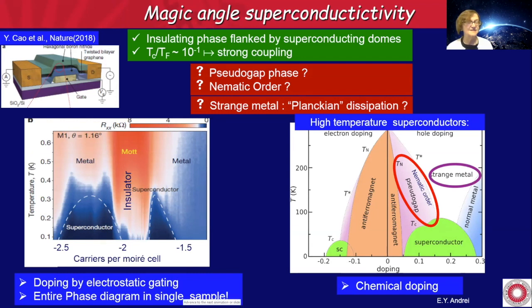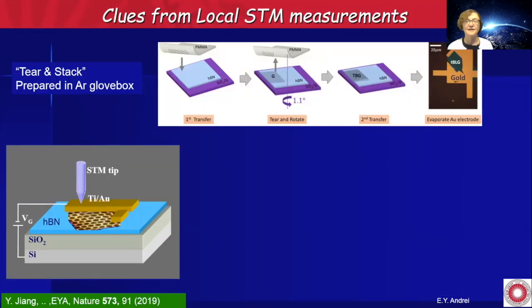This is a simpler system. Maybe it's going to help us solve the mystery of high temperature superconductivity. So we decided to look at it again. So this time we didn't use chemical vapor deposition graphene. We used exfoliated graphene. We treated it the same way by the tear and stack technique, but we omitted putting the top boron nitride layer on top so that it allowed us to look at the sample with scanning tunneling microscopy, which allowed us to look at the density of states of this system.